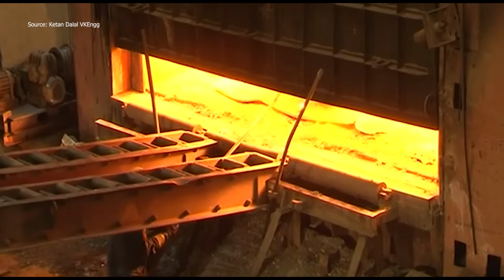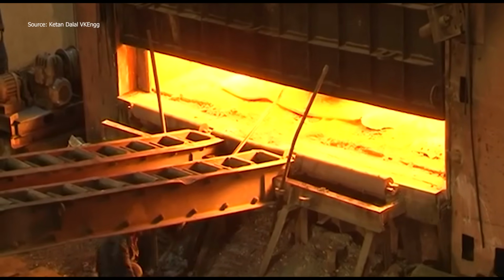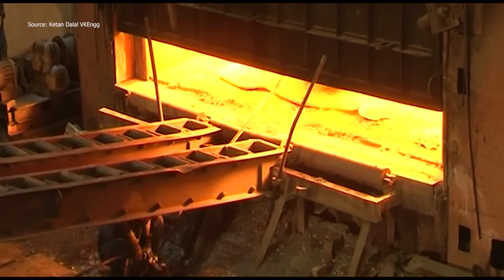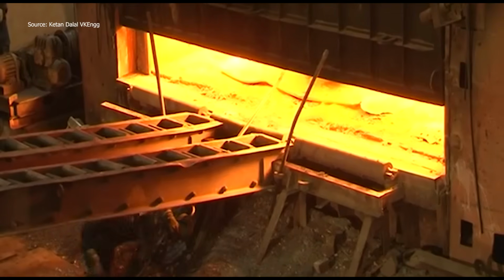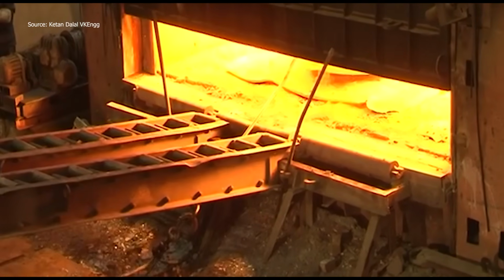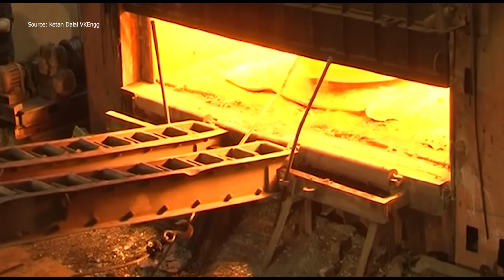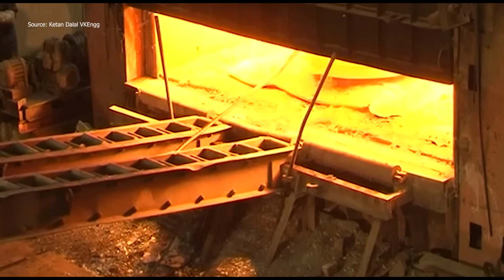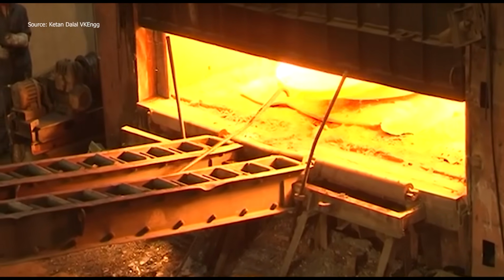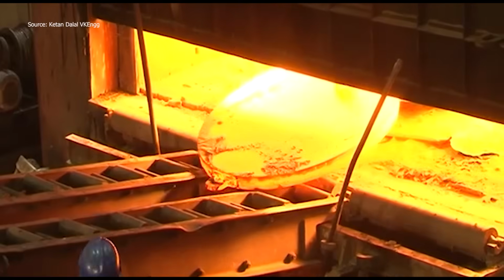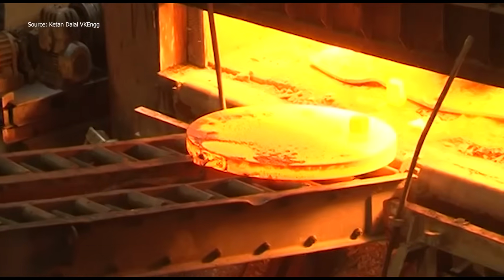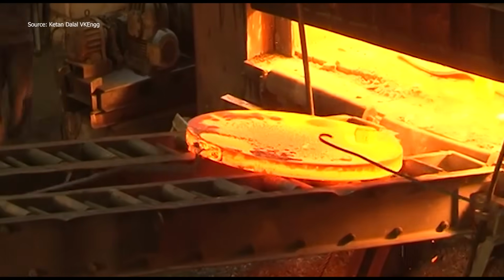This isn't brute smashing. It's carefully controlled pressure that allows the metal to stretch and flow into a smooth, curved profile. Throughout the cycle, hydraulic pressure can exceed hundreds of tons. Operators monitor the forming depth and flow to ensure perfect symmetry. No folds, cracks, or thinning.